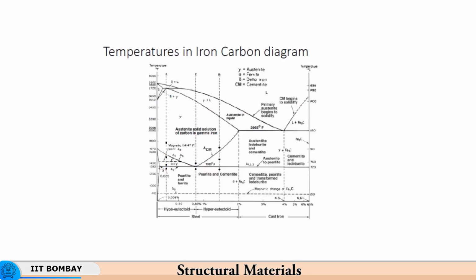So, heat treatments can never be delinked from the phase diagram. So, if you look at the different temperatures in the iron carbon diagram, you have the melting point at around 1540 degrees centigrade, and then as the material cools down, depending on the percentage of carbon, you will get different kinds of microstructures. For example, in this case, if it cools from this particular point, let us say this is the chemical composition of certain percentage of carbon.